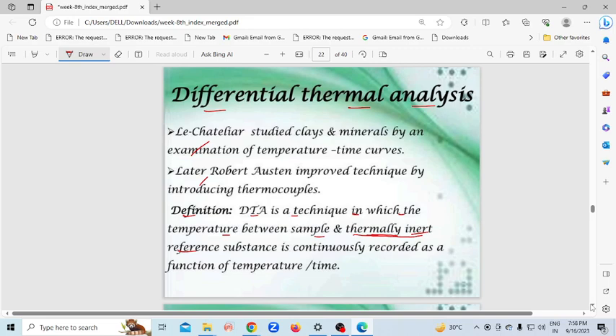Okay, it is continuously recorded as a function of temperature and time. Okay, so what are we measuring? We are measuring delta T. Okay, and why will delta T occur? Because your reference is inert, but your sample takes energy at a particular temperature. Okay, so at that time the temperature will be different in the sample and reference. So this delta T will be measured and you will plot it against temperature and time, and you will get some peaks, and then you will correlate this peak with your sample. Okay.